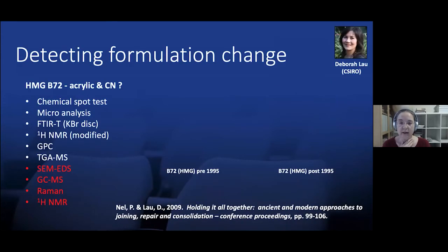I was very concerned about this outcome, and I went to a lot of trouble to double check whether I had mixed up my samples. However, this test remained positive. So when I raised this issue at a conference, I was supported by a government organisation called the CSIRO to investigate this issue further, and ultimately proved that cellulose nitrate was added to what is supposed to be a conservation grade adhesive, B72. However, there was a formulation change that occurred in 1995.